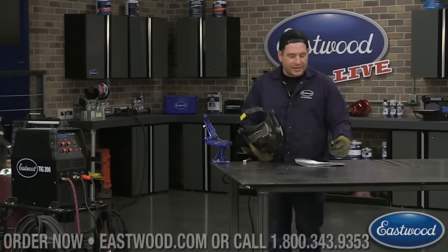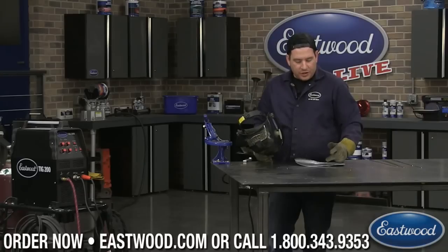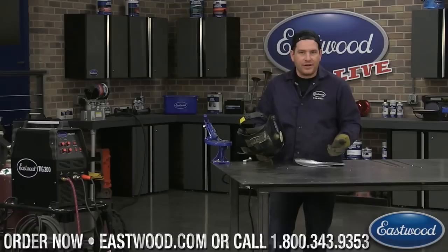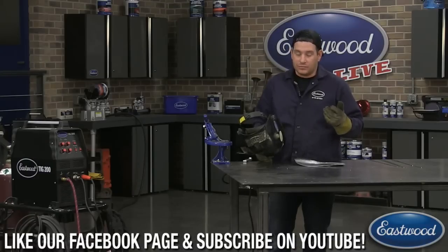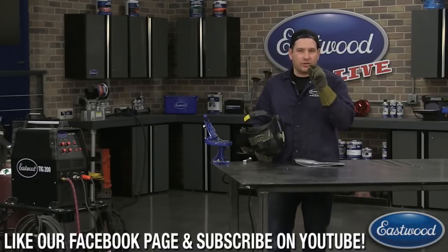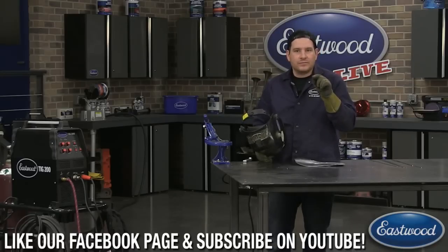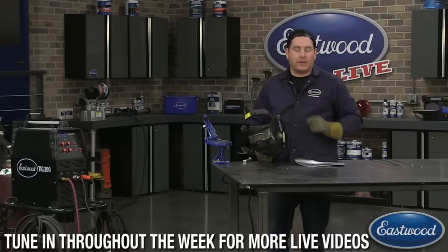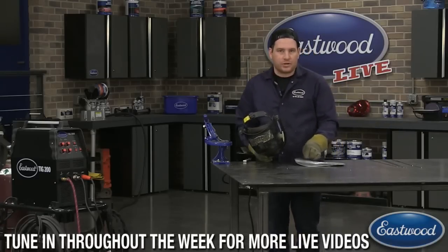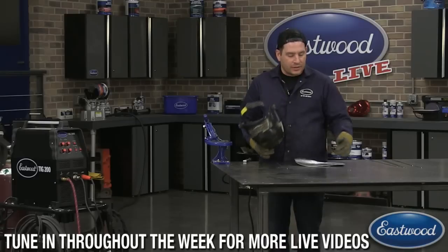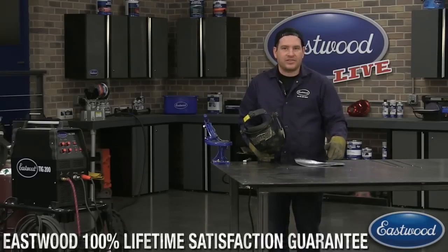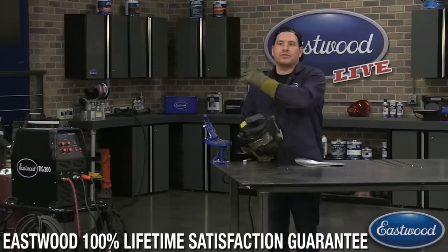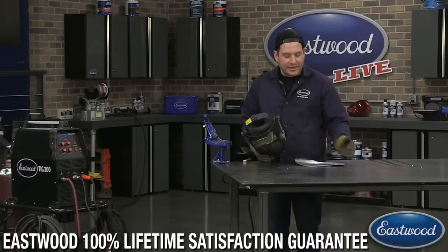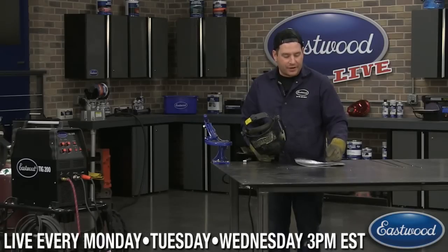One of the reasons I like to do that is because if you terminate in the center of that puddle and you come off too quickly, it can leave a crater. And if you go far too quickly, that can create tiny cracks in the weld that can then break right through the center of that weld. So if you imagine this was a weld joint we were welding on, like a butt weld, if we got a crater right on the center of that, it might be prone to cracking and go right through the center of your weld. So by going off to the side, it's giving a little area where we know that it's nice and solid, and the weld is good in the center of the joint.